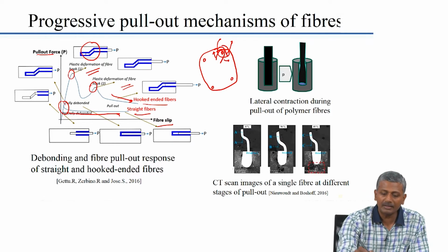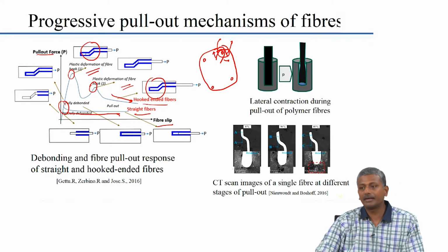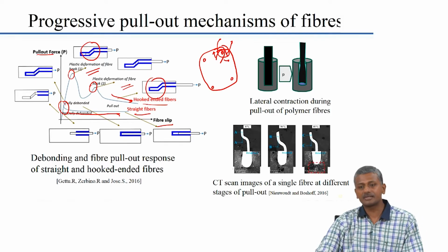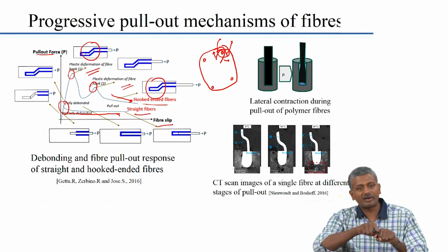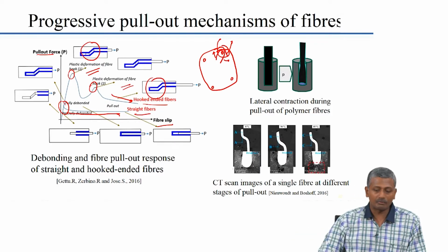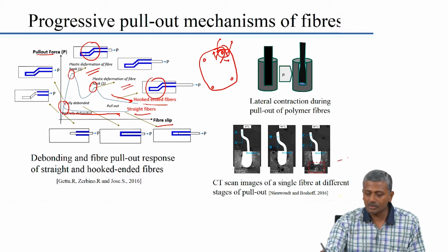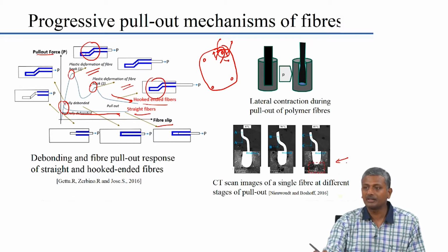Okay. Similar to that, having hooks at the end are really helpful, because the straightening of the hook is able to absorb a lot of energy before the fiber starts deforming and getting pulled out of your system. Okay. Again, this is actually a X-ray microtomography study which looked at the deformation that was suffered by the fiber before it got really pulled out of your system.